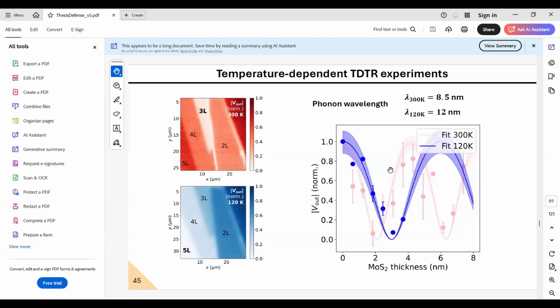And the fit is using an Airy function. So basically what you would use in a Fabry-Perot resonance cavity. So it's a transmission function with the Airy function, and we can retrieve the wavelength as we have how the thickness changes the amount of signal. I see. Okay, I see.